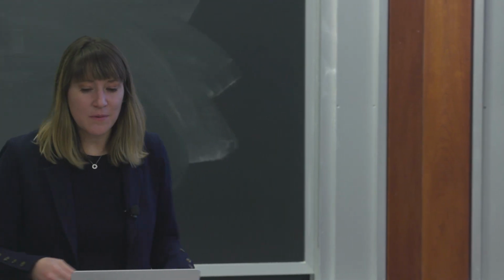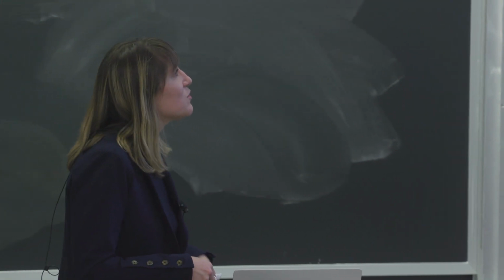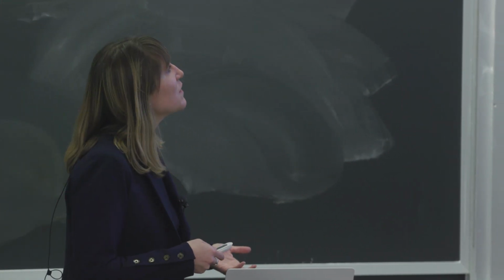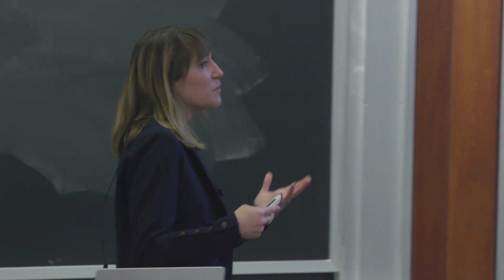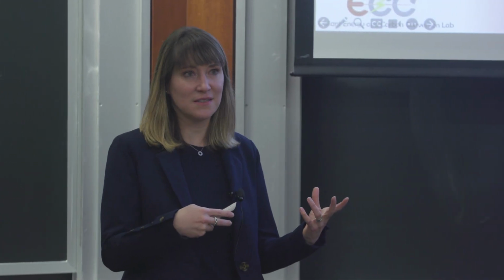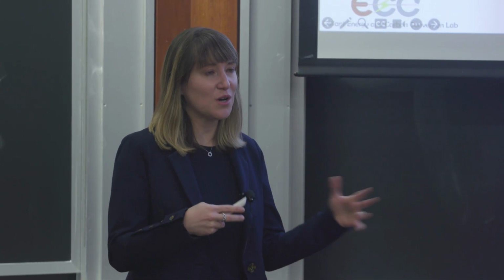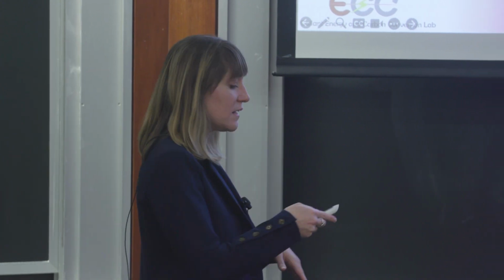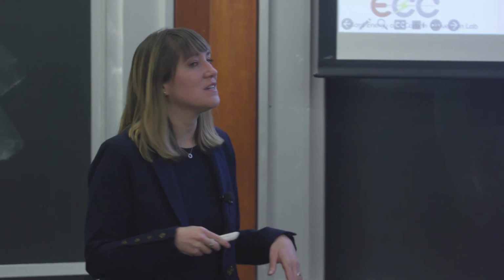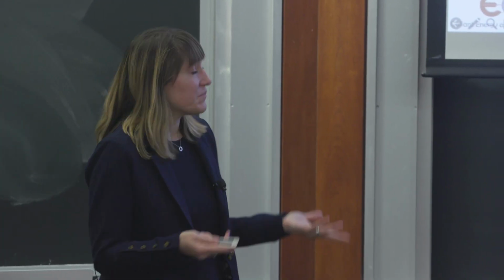So if it's true that lithium oxide is the SEI phase that most strongly correlates with Coulombic efficiency, we should be able to exploit this to design new electrolytes that are oxygenated and impart lithium oxide to the SEI, and demonstrate that we can reach comparable performance as the fluorinated analogs. And this would be quite compelling if we're able to do that, because fluorination is expensive and requires quite toxic synthesis.